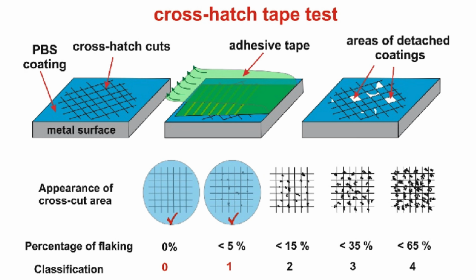Poor adhesion. When adhesion is poor, there is a weak layer, or layers, in the coating system that may be the cause of major damage in the future. Over a large surface, the coating may appear very uniform and seem to adhere well, isn't flaking off or bubbling, but when damaged, it may show that the coating is only loosely attached to the surface underneath. A crosshatch test will reveal poor adhesion by peeling off entire squares of the grid, and sometimes even beyond.